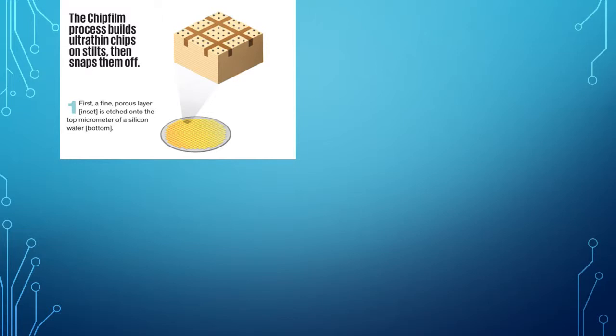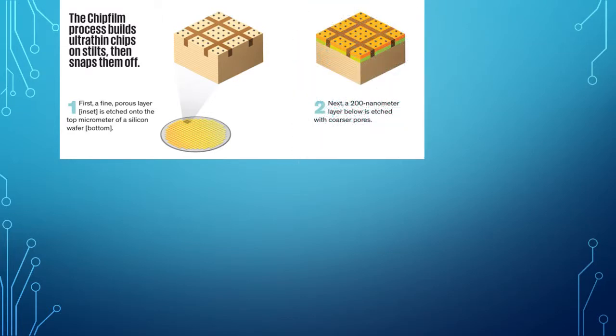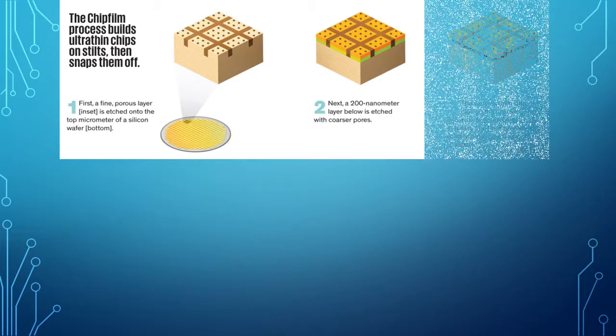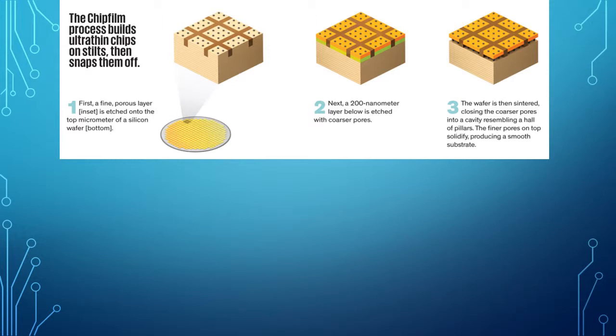First, a porous layer is etched onto the top micrometer of a conventional silicon wafer. Next, below this top layer, a 200 nanometer layer is etched with coarser pores. This is followed by sintering of the wafer at high temperature, which means that the coarser pores close into a cavity. It's kind of like a hall of pillars, with the pores being the pillars and the hall being the cavity. This produces a high-quality smooth substrate.